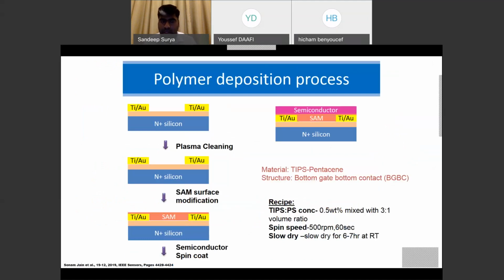There was a little tweak needed. Like I've shown you before, this is a bottom gate, bottom contact structure. I'm not going to repeat everything, but what I wanted to show you is how we deposited, because TIPS-Pentacene requires some SAM layer before you deposit the TIPS-Pentacene P-type semiconductor directly on top of the substrate we have.